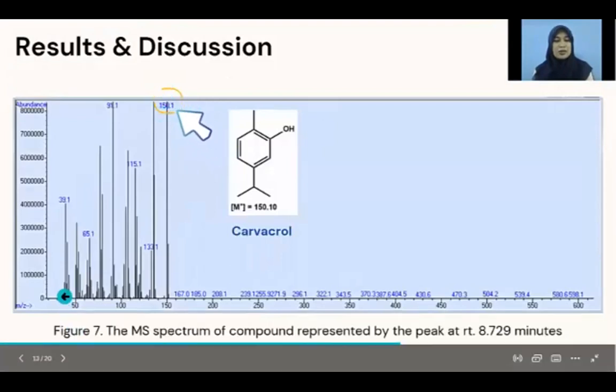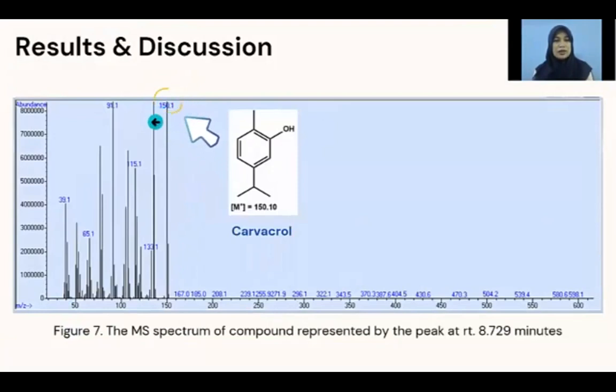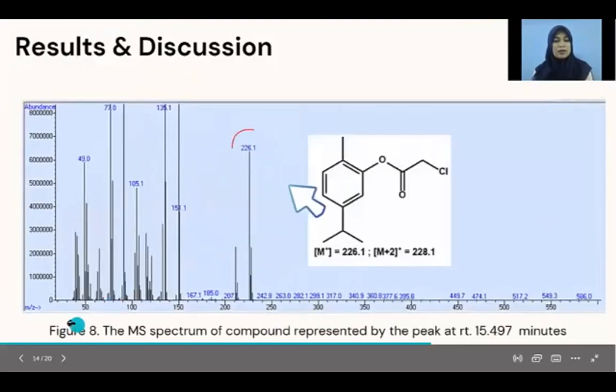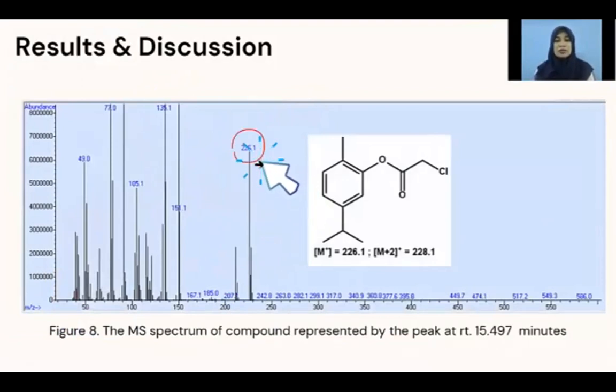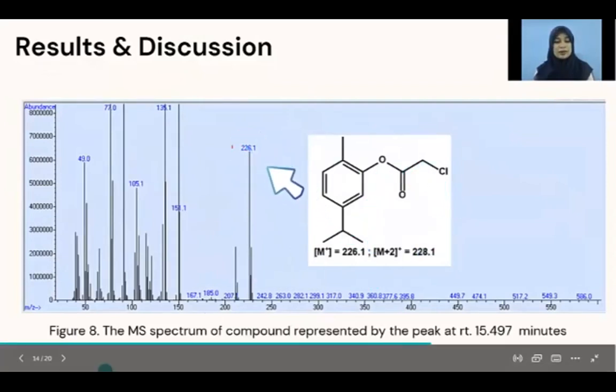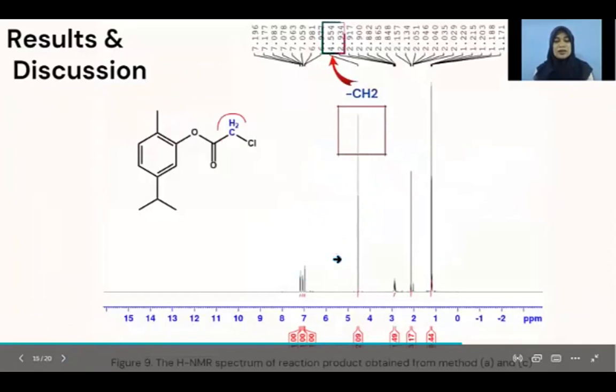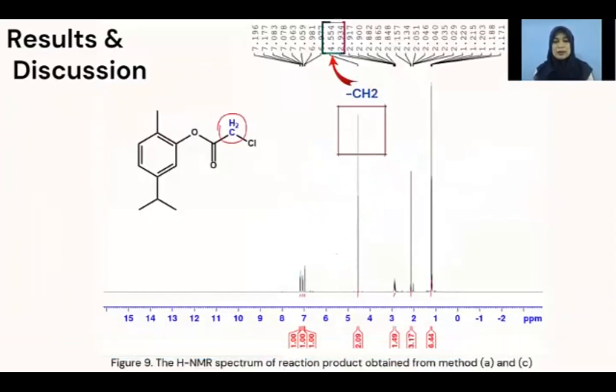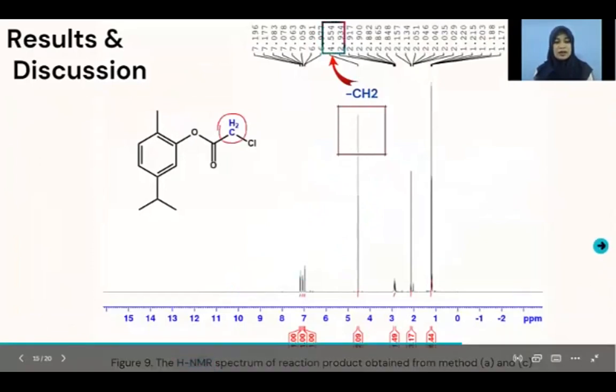Figure 7 also shows a peak with M/Z value of 150.1, which corresponds to carvacrol. Figure 8 also shows a peak with M/Z value of 226.1, which corresponds to the molecular ion of carvacryl ester. The structure of carvacryl ester was also confirmed by proton NMR data.